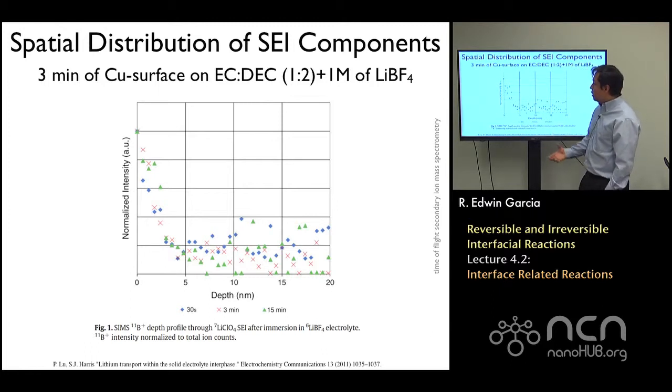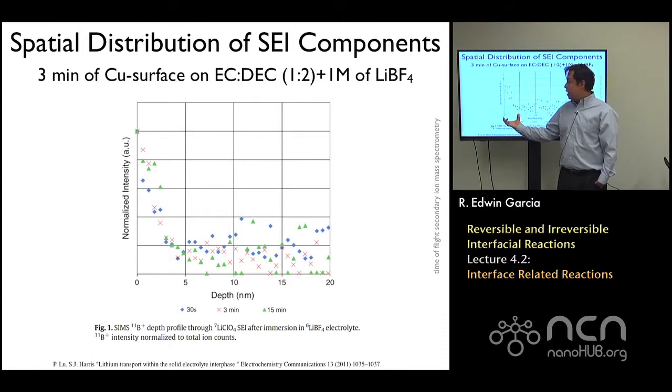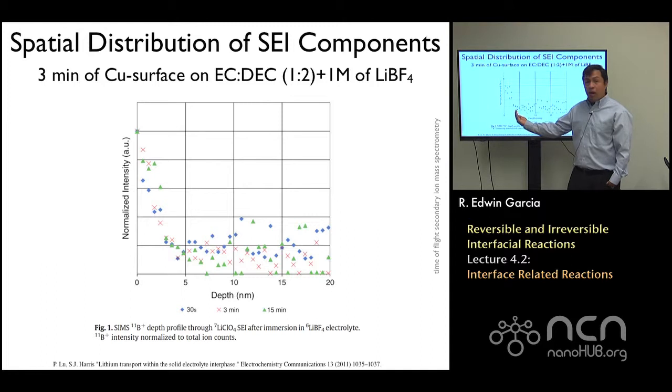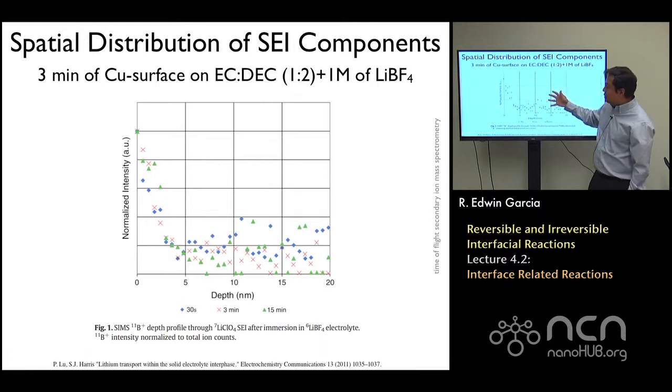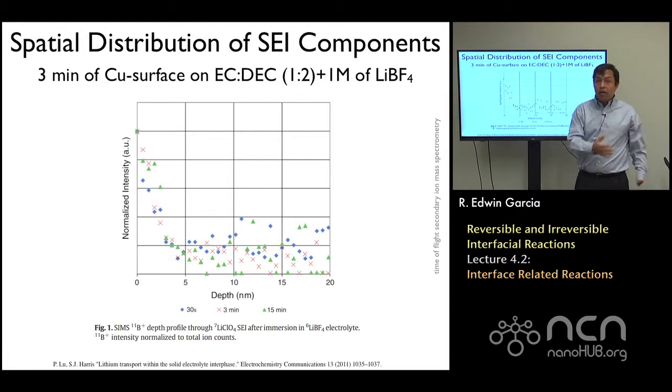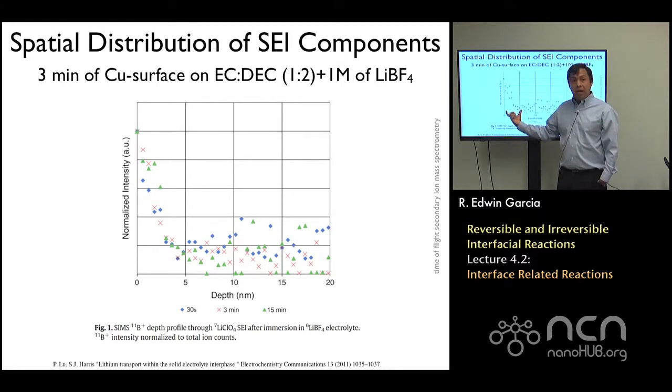And what people find is that the SEI layer very close to the surface is very dense, and as you get away from it, it becomes more and more porous, suggesting really that the lithium ions, besides going through this very large porous network of particles, when they get here, have to traverse this local nanoporous region where they end up reacting very close, in this 5 nanometer region.